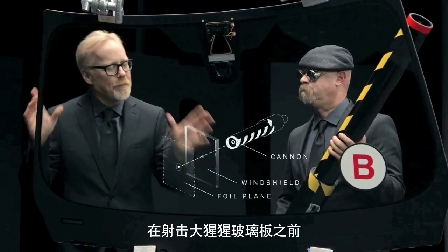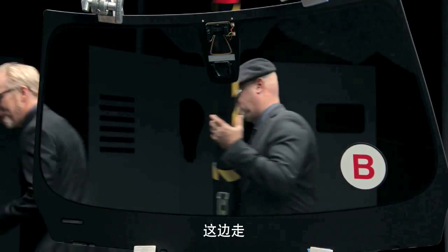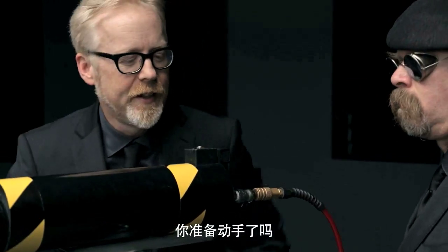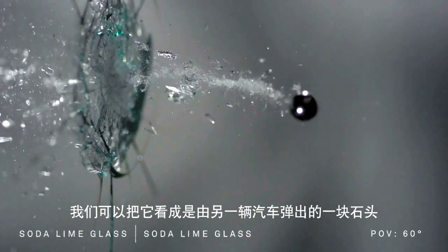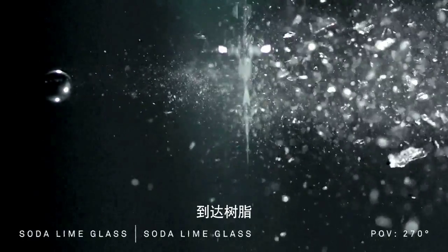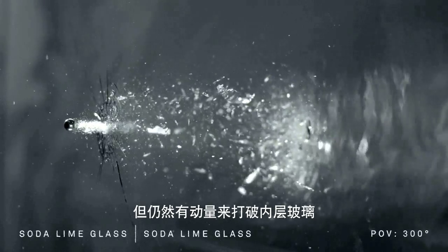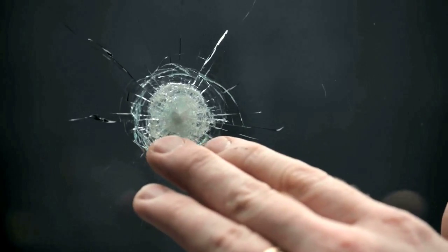When do I start shooting? Before we shoot the Gorilla Glass laminate, let's shoot the regular soda lime laminate — windshield A. Three, two, one, go. Whoa — that was a lot of damage. The ball bearing hits the windshield at around 120 miles per hour — this could be a stone flicked up by another car. It penetrates the exterior glass, stretches the resin, and is slowed down a bit, but still has enough momentum to break the interior glass layer, causing small fragments of glass to spray out through the interior of the car. Not good.